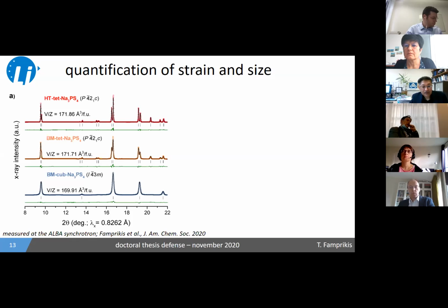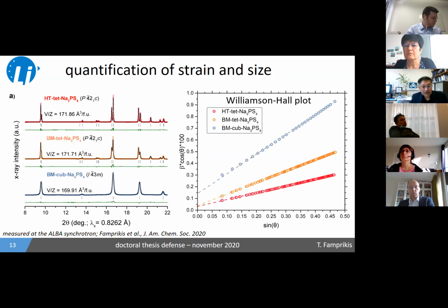You can see directly from the positions of the Bragg peaks, if we do a quick fit, that there is quite a bit of a difference in volume from the cubic sample. So the two tetragonal samples are more or less the same, but the mechanochemically synthesized sample shows a lower volume. We went on then to analyze the shape of the Bragg peaks to get microstructural parameters for our powders. And this is better shown in what is called the Williamson-Hall plot.